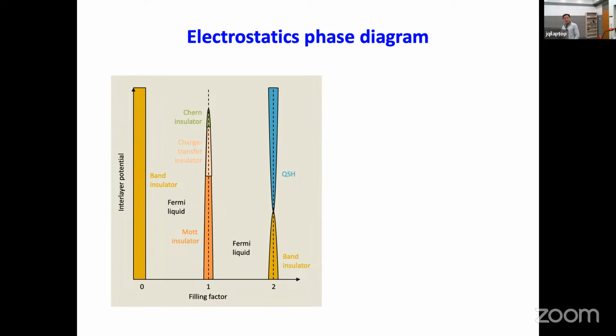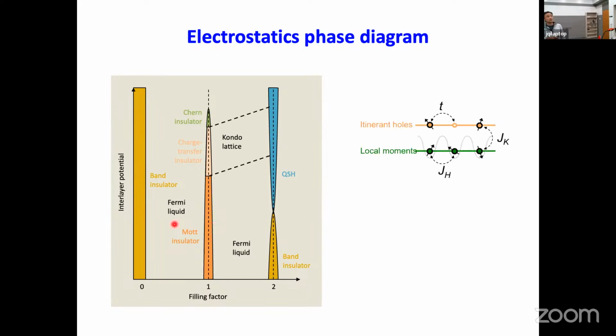And then by looking at this phase diagram, you would expect the Kondo lattice physics to appear just by doping on the right of a charge transfer insulator, where the charge carriers will go to the tungsten layer. And it makes a certain slope because of the finite electron density of states of the tungsten layer. Okay, so that's where we expect we have a Kondo lattice in the system.